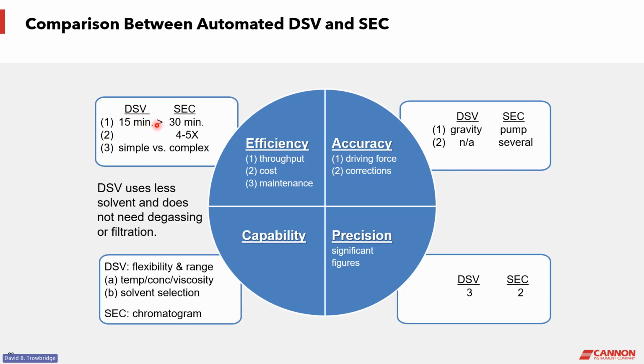Throughput for a DSV, I'm going to just say, is in most cases half of what it is in SEC. SEC can run to 45 or 30 minutes, and this can go down to 10 minutes. So there's some flexibility there, but that's a good ballpark comparison. Cost, the SEC is going to be at least 2 times more expensive than the DSV, and 4 or 5 times more depending on the configuration, the amount of columns that you use, and that kind of thing plays into it. Regarding maintenance, well, the DSV is actually more simple to maintain and more simple to operate. There's just less moving parts, whereas SEC is rather complicated.